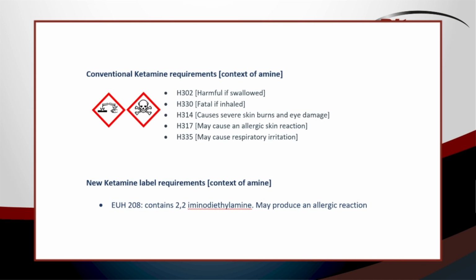In the case of the conventional ketimine, K1, in its supply form, it has a free monomeric DETA level of around 2 to 5%, subject to the supplier specification, the process employed, and the subsequent storage conditions. With exposure to moisture, the reaction liberates further DETA for reaction purposes. The ketimine reversal reaction liberates approximately 35% of monomeric DETA. One version of the new ketimine epoxy curing agent has been formulated so the initial free amine level is less than 0.2% as supplied. And following the ketimine reversal reaction, it liberates still less than 2% of monomeric amine as analysed on hydrolyzed product.